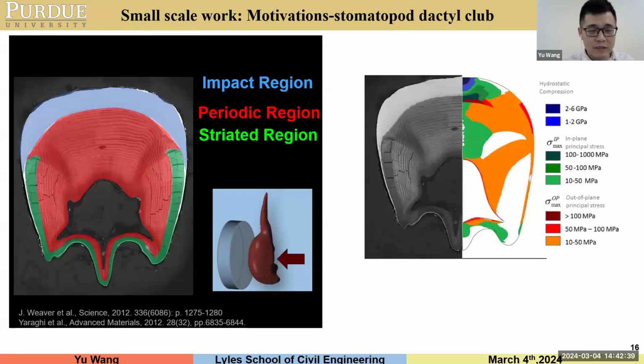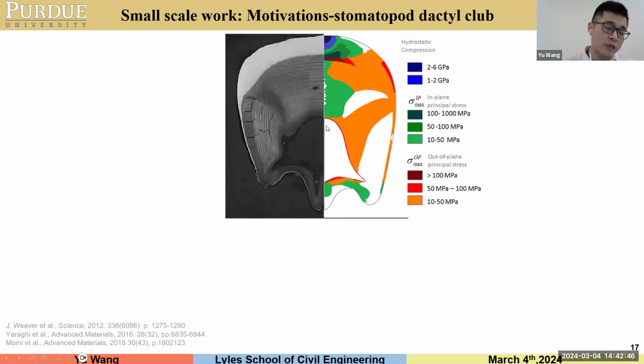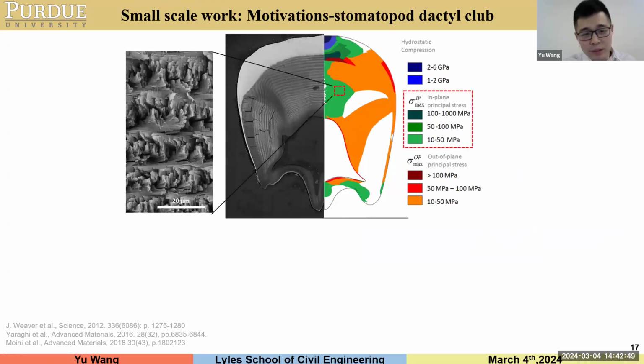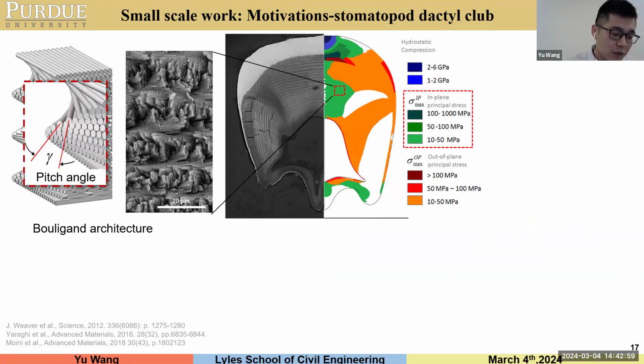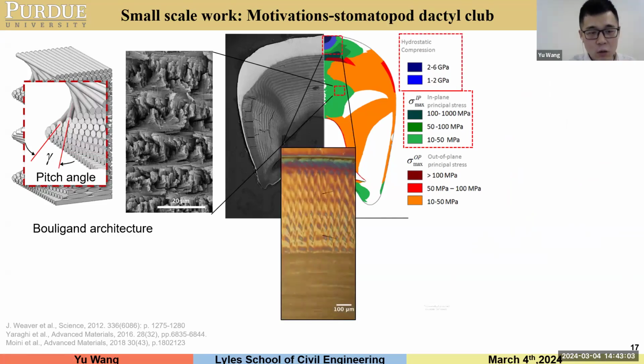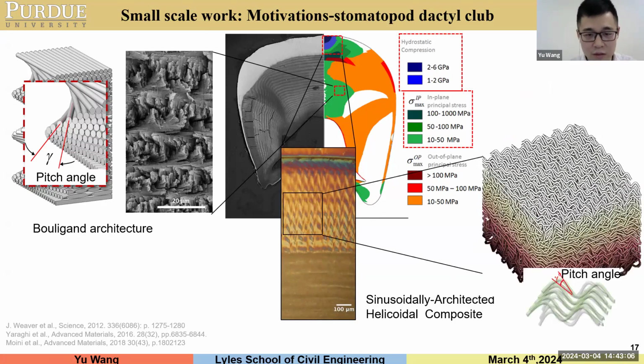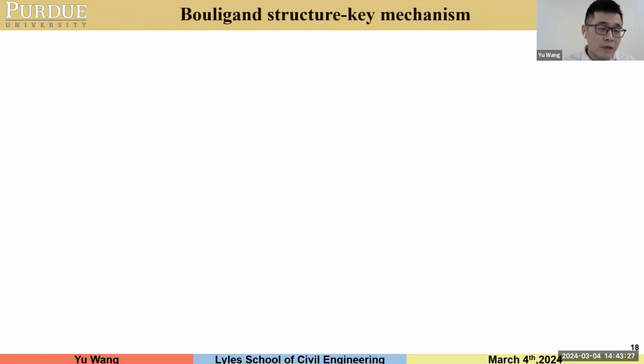If we run a simulation of the impact behavior of the mantis shrimp, we can get a stress distribution contour like this. In different regions, there are different architectures. In this green region, the researchers found an architecture we can call the Bouligand architecture. And in this blue region, which undergoes high compressive stress concentration, there's another architecture, which we can call the sinusoidal, helicoidal, or herringbone architecture. So can we use this architecture with 3D printing concrete to improve the energy absorption capacity of concrete and provide our concrete with a novel functionality? We start with the Bouligand architecture.